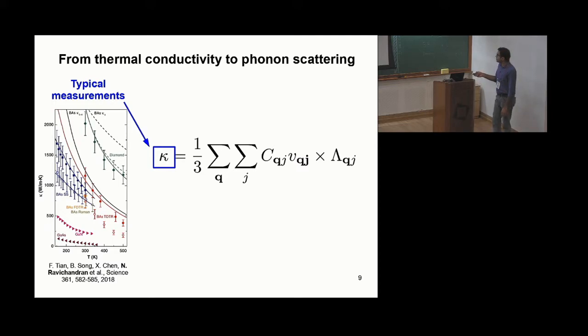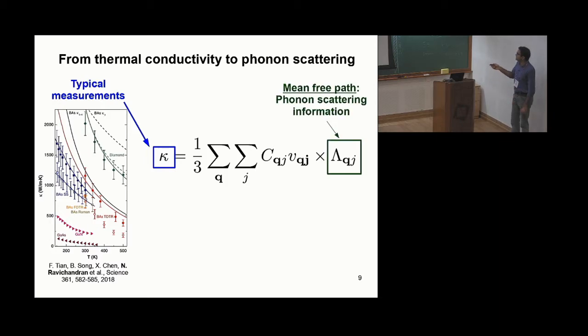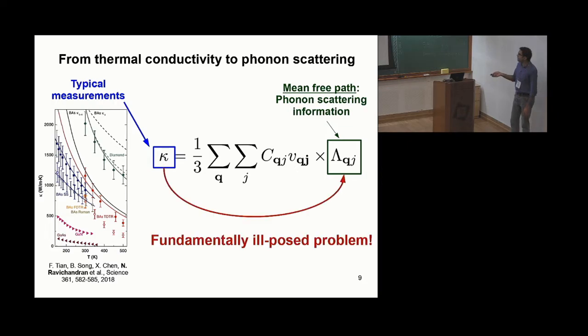But if you want to get these phonon-specific quantities, you can clearly see that it is an ill-posed problem. More precisely, if we want to get the mean free path, which contains all the scattering information that phonons undergo in a material, this problem is fundamentally ill-posed. Why? Because you have a single equation for thermal conductivity, but a large array of unknowns, so it's not possible to invert this equation.